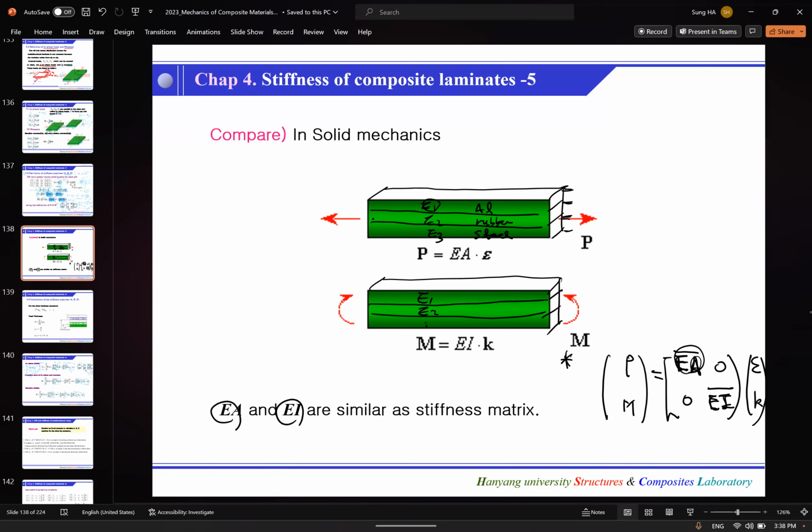With different material properties like this, under tension, you can imagine that this beam will not extend straight. This can bend under tension because we have an unsymmetric material property. So under this tension load, this will extend. Extension like that.